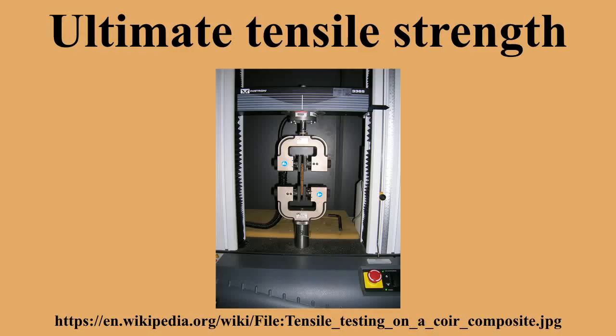It should be noted that, while most metal forms, such as sheet, bar, tube, and wire, can exhibit the test UTS, fibers, such as carbon fibers, being only 2/10,000th of an inch in diameter, must be made into composites to create useful real-world forms. As the data sheet on T1000G below indicates, while the UTS of the fiber is very high at 6,370 megapascals, the UTS of a derived composite is 3,040 megapascals, less than half the strength of the fiber.